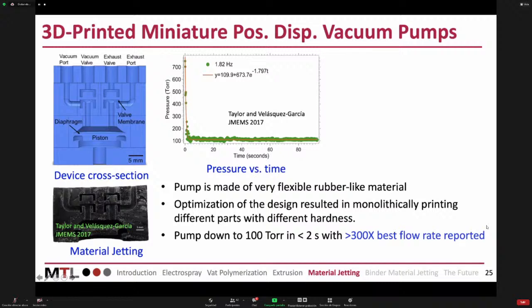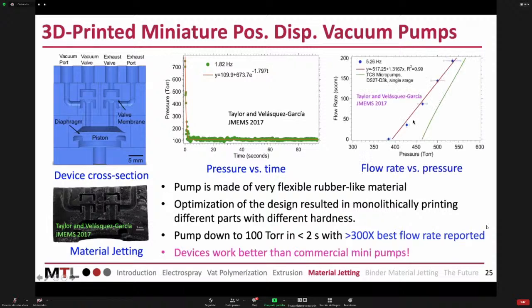And that's a compression ratio of 8:1. And on top of that, you also move a lot of flow rate. But what is truly amazing is that our devices work better than whatever is commercially available for a comparable size, of course. And what you see here is that if you have a given pressure, our devices can actually move a lot more flow rate. So what you see again is that making hardware via 3D printing enables you to make better systems. So there are examples where this doesn't work, of course, but we just choose the examples where it makes sense to 3D print. And we show that because of the performance, it makes sense.